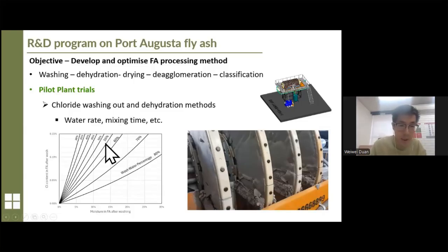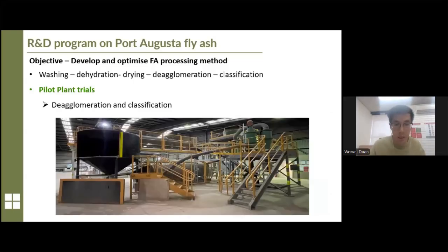And also we're looking at the water ratio and the different operation parameters, including the water rate, how much water we use to wash out the fly ash, and how long we should wash the fly ash. And we also try to get some relationship between the chloride content left in the washed fly ash versus all these parameters. So that's the result we are trying to get. And that's the photo of the de-agglomeration and the classification equipment in the pilot plant.